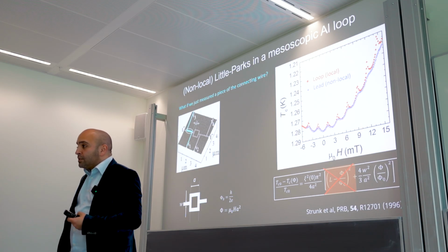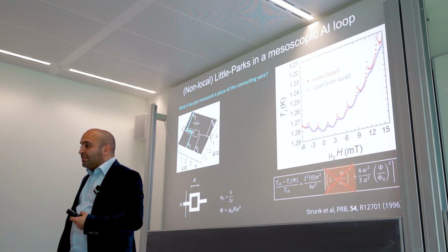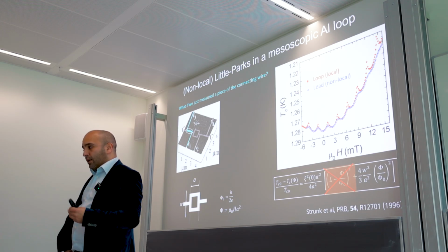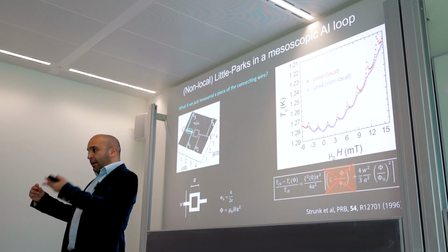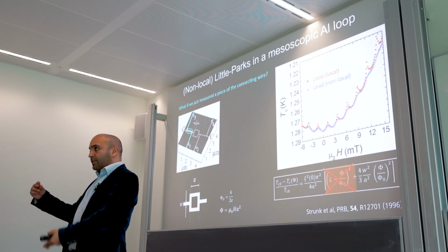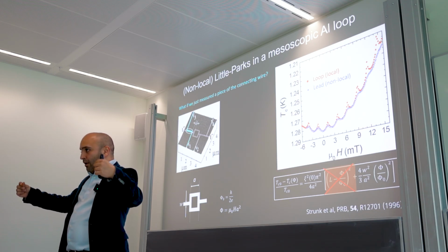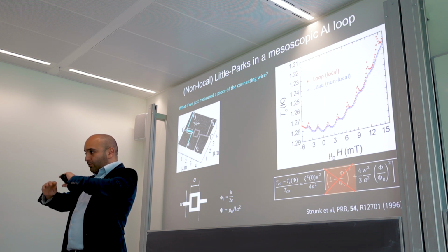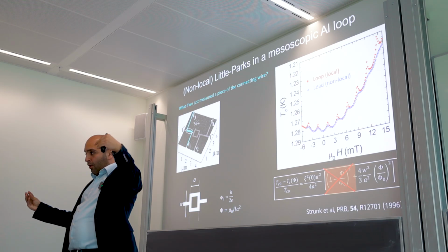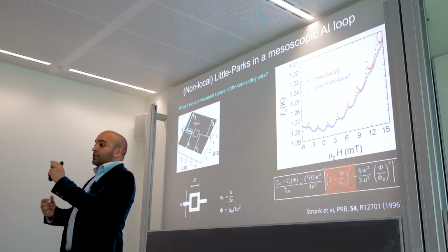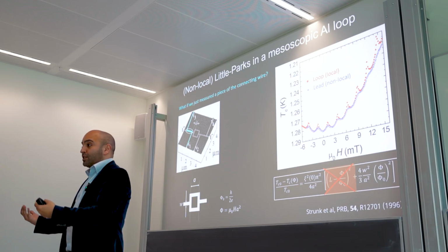Yes. If this was not such a short structure, if it was taller, say a cylinder, would it still be the same? It would be exactly the same. Because the original experiments in the 60s, they didn't have nanofabrication and thin films. So you know what they did? They got a glass tube and evaporated, I think it was tin, on this glass tube while rotating it by hand. That way they got a thin-wall superconducting cylinder around the glass tube, and that's what they contacted and measured Tc and saw the oscillation. It wasn't a thin film.